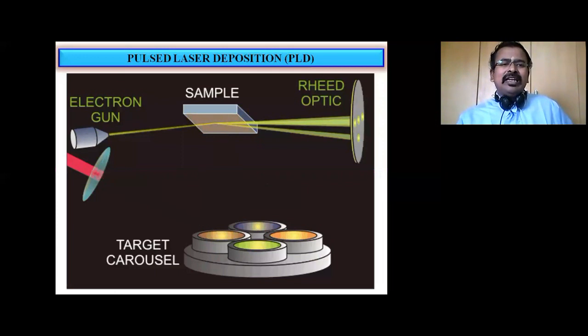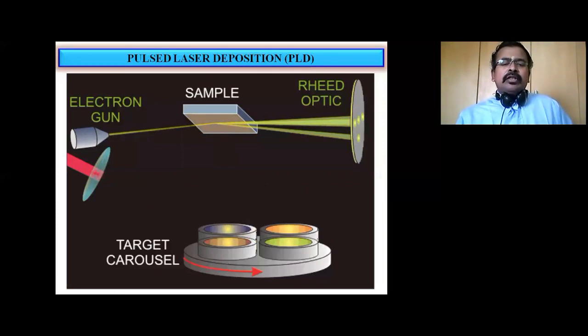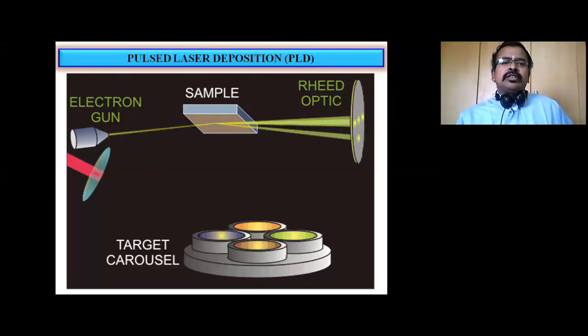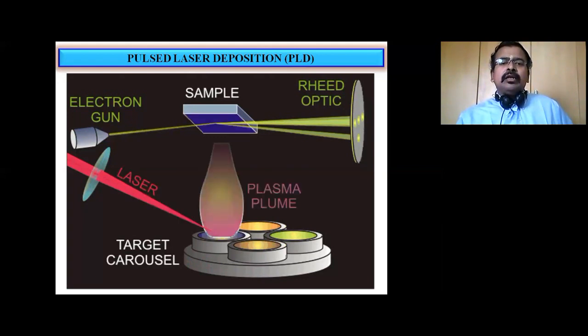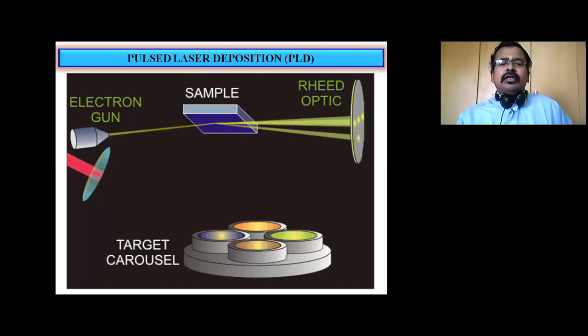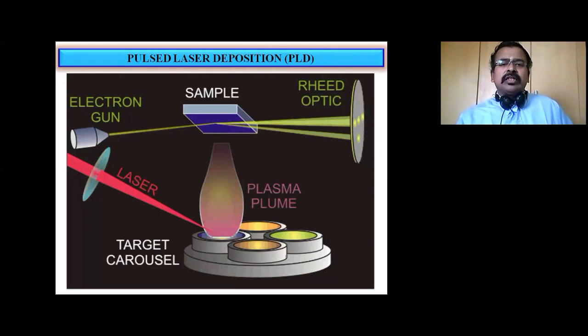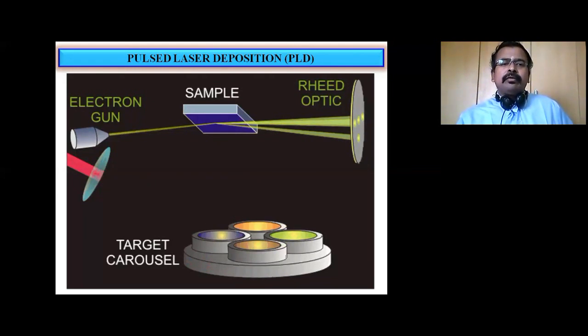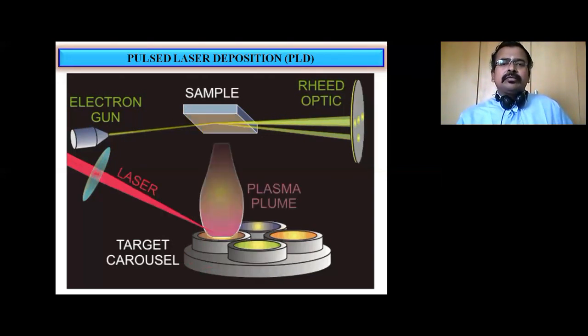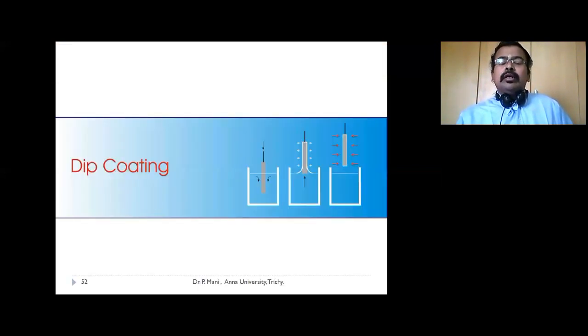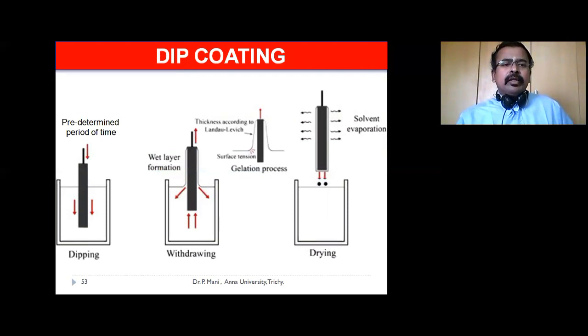With the help of a laser, the target is evaporated towards the sample, and we are using different elements to coat on the sample. With the help of the laser, it's evaporated and coated on the sample as a thin layer on the substrate. Okay, then we may go to dip coating. Here we are having a step-by-step process of coating.